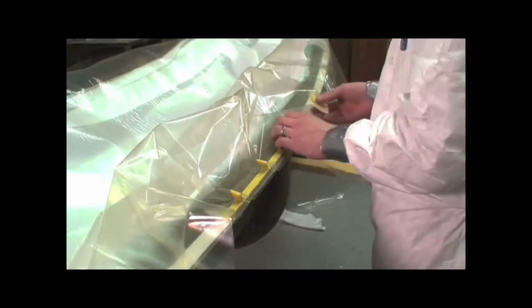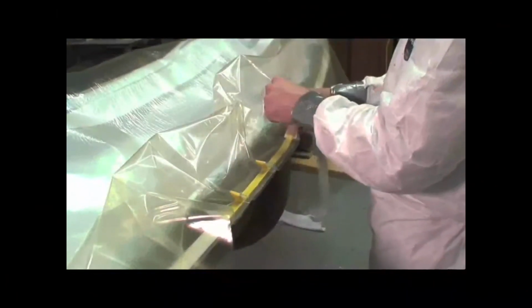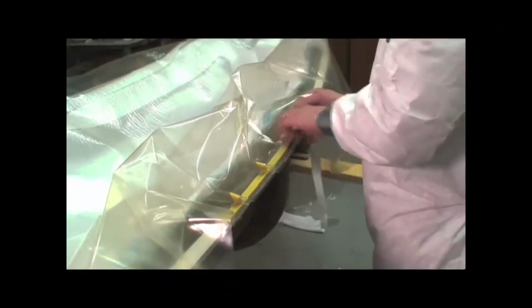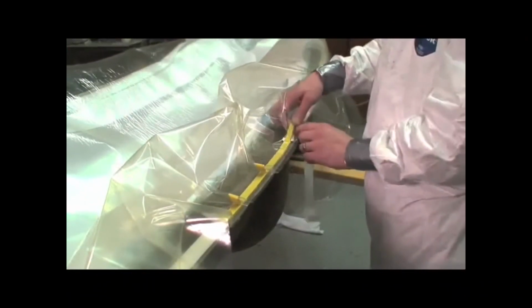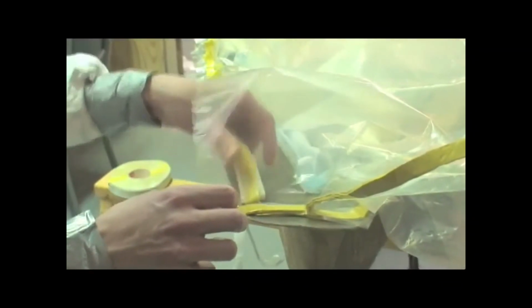To start, we found the center of the film and stuck it down to the center of the mold with a vacuum sealant tape. We worked the film from the center out, making pleats in the bag every few inches. The number and size of pleats is determined by the complexity of the part's shape. The vacuum bag film at the ends of the mold was sealed to itself and then to the mold.